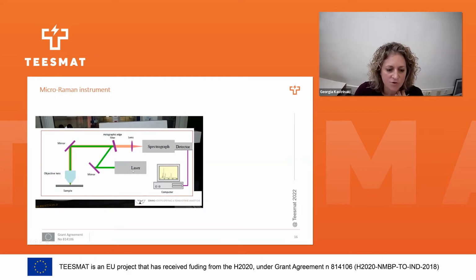When you use it, you have a laser source, and by different mirrors, you just follow your beam into the sample. You focus onto your sample, and you define what part of the surface you want to study. So literally, you see the microstructure, let's say, of your sample by a lens, and then you focus the beam, and then by backscattering, you follow the Raman part into a holographic edge filter where you open up your beam, and this is led to the spectrograph, the detector, and the computer, and the computer gives you this Raman spectra ready to use.